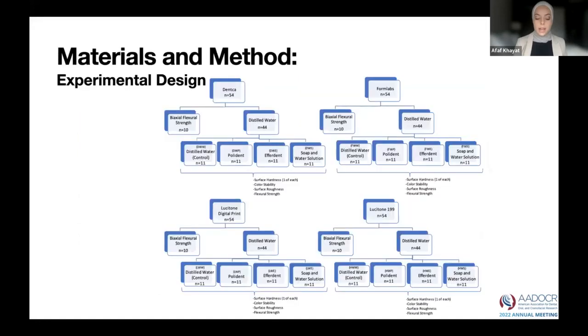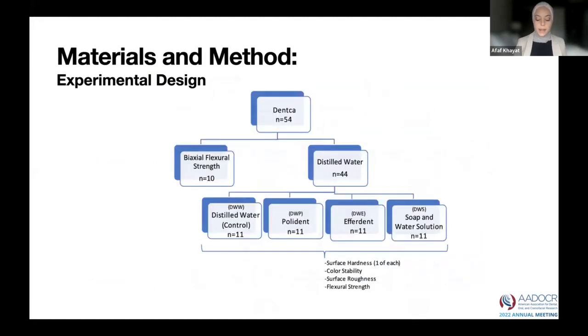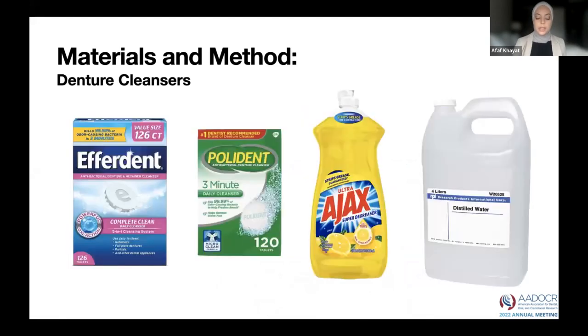Specimens of each resin type were divided into 4 groups according to the denture cleanser treatment they would be exposed to. 10 specimens underwent baseline biaxial flexural strength testing. 1 specimen of each group was used for surface hardness testing, and the other 10 specimens were used for color stability, surface roughness, and finally biaxial flexural strength. 4 cleansing solutions were used in this experiment: Efferdent, Polident, dish soap, and distilled water.